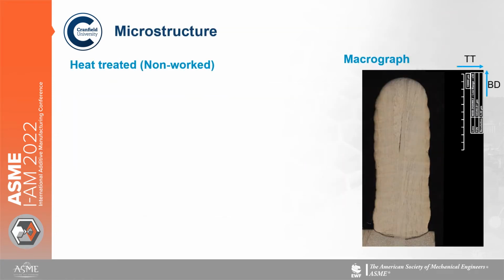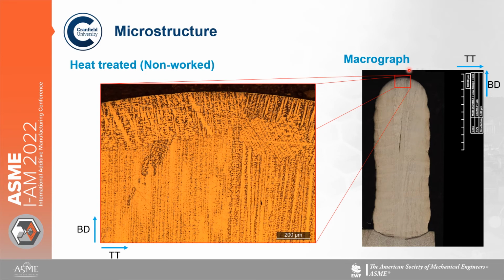The microstructure of our samples. So firstly, we're going to take a look at our heat treated only sample, which is our non-worked condition specimen. So you can see this is in the through thickness build direction axis, which is just a cross section through the thickness. So on the macro, you can start to see our columnar grain structure. And if we zoom in on the very top here, you can see the final deposited layer of material. And you can also start to see some of the dendritic structure of the grains as well, mostly orientated in the build direction.